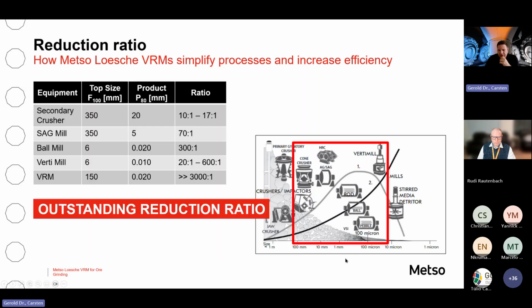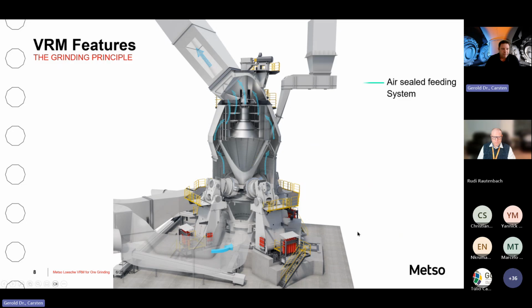And the VRMs have an outstanding reduction ratio. You see within that red square that basically you can start feeding the mill with any of the given sizes. You can feed it very coarse if you have a soft material, but you can also feed it with 150 micron if you want to grind iron concentrate for iron pelletizing. So it's a really flexible piece of equipment.